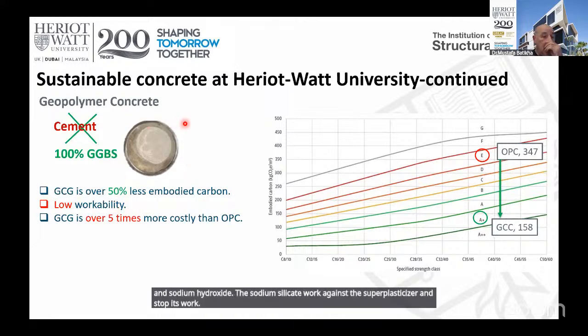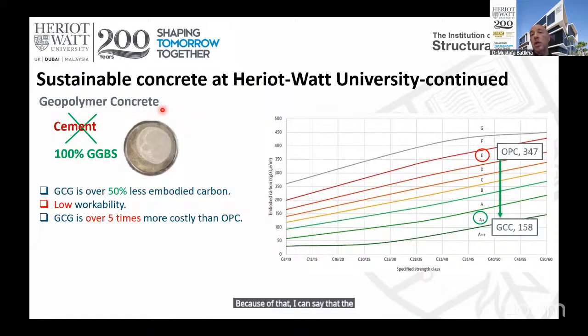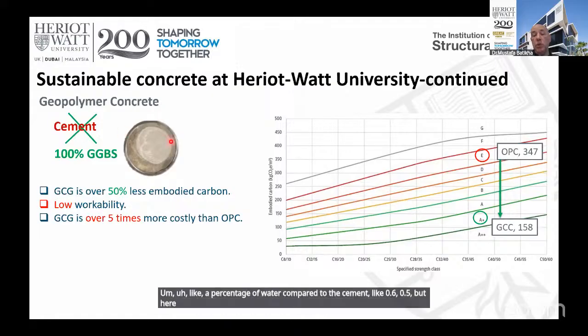Because of that, I can say that the geopolymer concrete can be used with low strengths, because in low strengths you use a ratio of water to cement like 0.6, 0.5. But here in our mix, we use about 0.33, and the stopped working of the superplasticizer gives low workability.